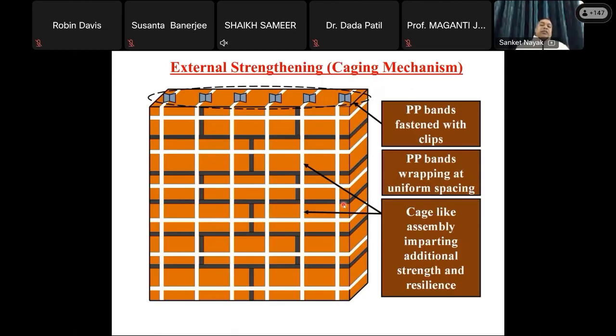Whenever we are talking about this external strengthening mechanism, it is a caging type of thing. You can see that these PP bands are fastened with the clips, and they are wrapping around, and it will make a cage. Just like if there is a stack of books and we give a lateral push, the stack of books can fail. But if you tie it up and try to push it, then you require more force, and even the failure of the individual brick may not be allowed. So that is the technique that we try to tighten it.